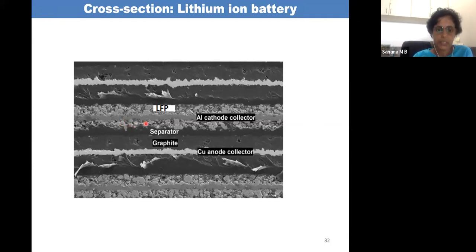In addition, the separator is soaked with the liquid electrolyte, and you can see that there are small pores over this. All these pores become a reservoir for the electrolyte. So these pores are important. Unless you have enough pore percentage, we will not have good cyclability, or what we call the power, I mean how fast we can charge or how fast we can discharge. The rate capability of the cells will not be good.